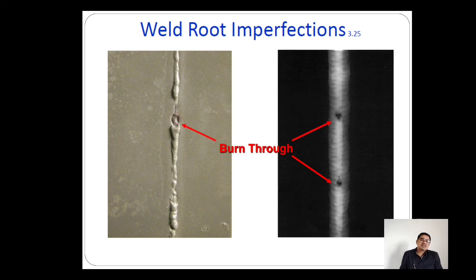So friends, you can see burn through like this in an actual plate. At a particular location, once the current is higher or for any other reason, the parent metal as well as the weld metal fall through the weld plate. So you can see such an indication, and you can also find a similar indication in the radiograph, on the very right side of this picture.